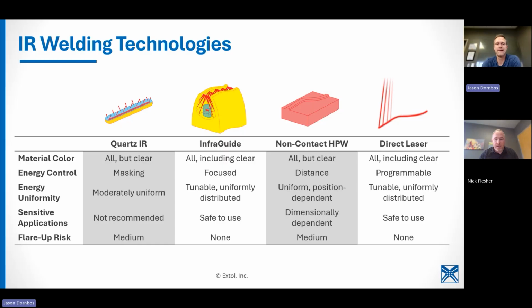So I will just say, generally speaking, IR welding can be a bit longer than certainly vibration. Vibration is really fast. It's come down, friction and press. It can be comparable to hot plate. So you saw the video of InfraGuide real time. We've run black parts with melt times in the 10 to 20 second range. We've run white parts with 22 seconds. So that's a little bit longer of a melt, but it all depends on how large your parts are, how dimensionally stable, how absorptive they are, what your strength requirements are, how much heat effect is on.